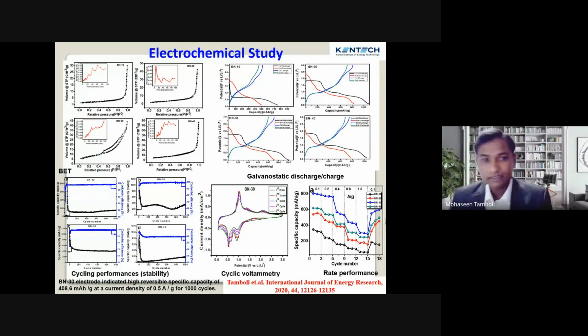After that, in the electrochemical study, the bismuth vanadate, nickel cobalt oxide 30% sample shows the highest surface area compared to the bismuth vanadate NiCo2O4 10%, 20%, and 40% electrodes. This is the BET data you can see in the corner. The special heterostructure of the BN30 electrode demonstrates significant electrochemical properties, maybe due to the higher surface area of the composite. Generally, if the surface area is high, it can develop more active sites, and if more active sites are generated, it increases the catalytic activity.